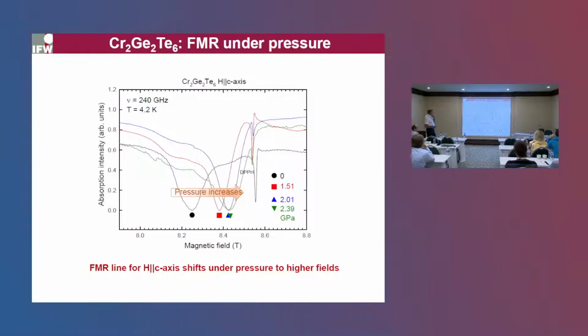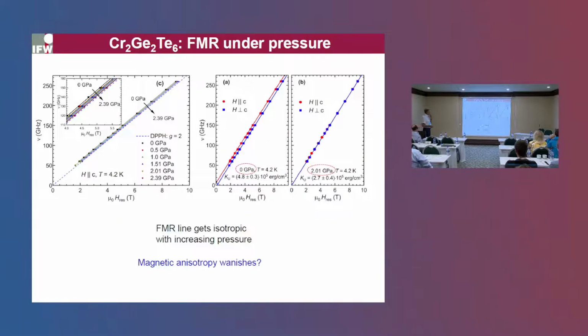This is, for instance, a ferromagnetic resonance line at a given frequency at ambient pressure. Now we apply pressure, and you see that the line continuously shifts to higher fields. So there is a distinct effect, a very appreciable effect of pressure. If we measure that at different frequencies, what we see is that with increasing pressure, it continuously comes to the isotropic limit. These are two distinct branches at zero pressure, and they merge into a single isotropic resonance response with increasing pressure.